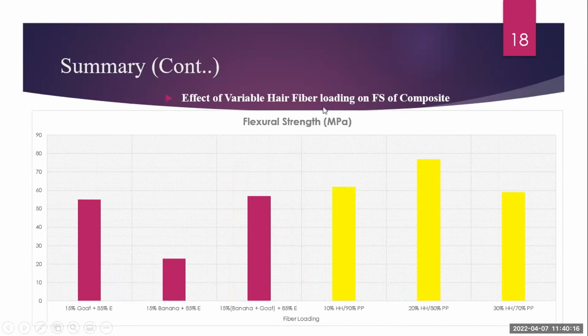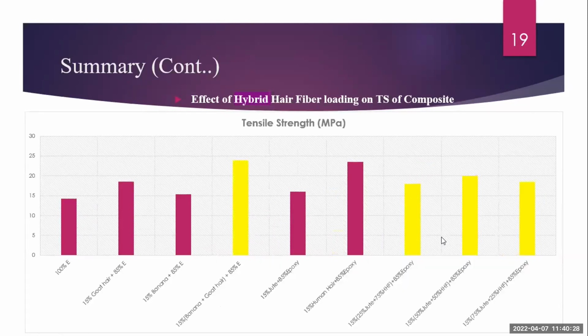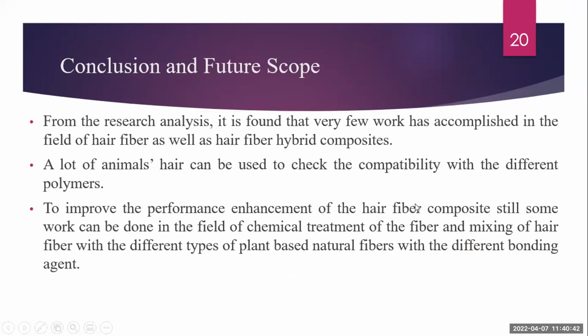Effect of variable hair fiber loadings on flexural strength. Also we can see that 20% of fibers mixed with 80% of polymer can also enhance the flexural strength property of the materials. Effect of hybrid hair fibers. If more than one fiber is used from the fabrication point of view, it can also increase the tensile strength as well as the flexural strength.